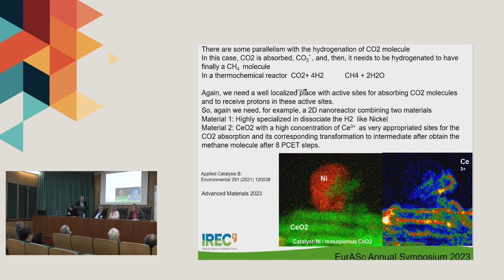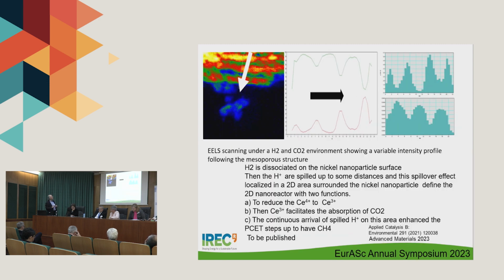For example, nickel, nanoparticles of nickel. And material 2, I need 1 site where the carbon dioxide can be blocked. And then I can make a shower of hydrogen, spillover of hydrogen. So, how to combine these 2 materials? How to get ceria +3, because if I have ceria +4, the absorption of CO2 is not good. So, this is one example of the design. I put nickel.